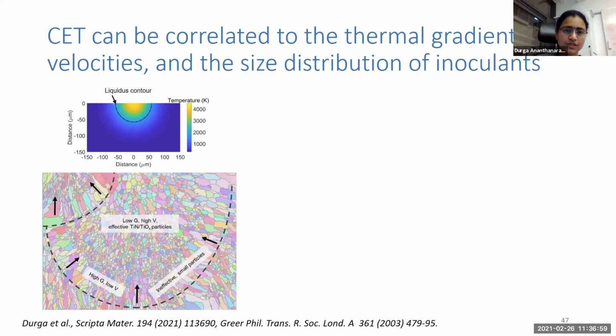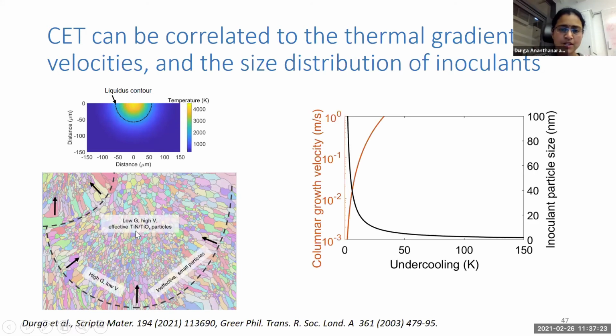So how do we relate it to the thermal gradients and the thermal conditions that we have? Typically in a melt pool, we have a high thermal gradient and low velocity at the bottom of the melt pool, and a low gradient and high velocity in the middle of the melt pool. From our experiments, we saw that we have very, very small particles in the columnar region, and in the more equiaxed region, we had bigger particles. This can be explained by this GRADE model, which looks at the inoculant particle size and the nucleation undercooling required for nucleating an equiaxed grain on this inoculant particle.